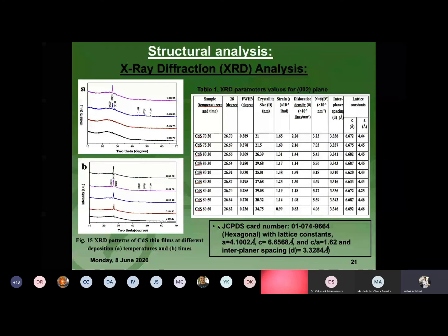For both cases, we are having a strong reflection, 002, at 2-theta value 26.7 degrees, which signifies the hexagonal structure of the film, resembling the hexagonal structure of the films. The other minor peaks, 100, 101, 110, 103, and 112, are also compatible with the hexagonal structure.